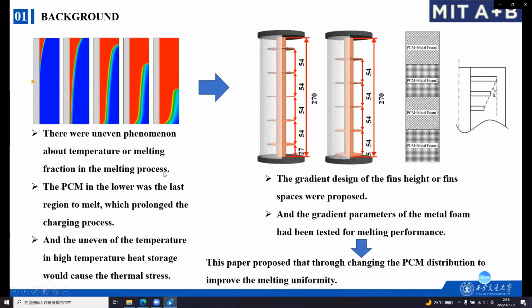In order to solve these problems, the gradient design of the fins or fin spaces was proposed, and the gradient parameters of the metal foam have been tested for melting performance, such as the gradient porosity and the gradient PPI. Except for the above methods, this paper proposes changing the PCM distribution to improve the melting uniformity.